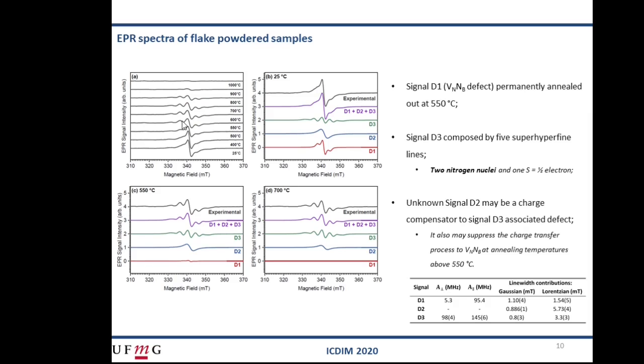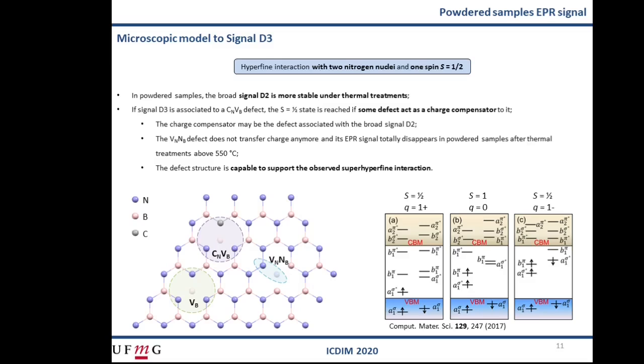It is possible that an extra point defect generated the signal D3, so that the thermal level is shifted and then the VNNB energy level becomes more isolated in the bandgap. To propose a point defect as responsible for the signal D3, two conditions can be imposed based on the observed EPR experimental data. 1. The defect needs to be capable of showing a super hyperfine interaction involving two nitrogen nuclei and an electronic spin one-half to generate the 5 lines observed. 2. It is possible that a vacancy associated with its structure warrants that the defect has good thermal stability.